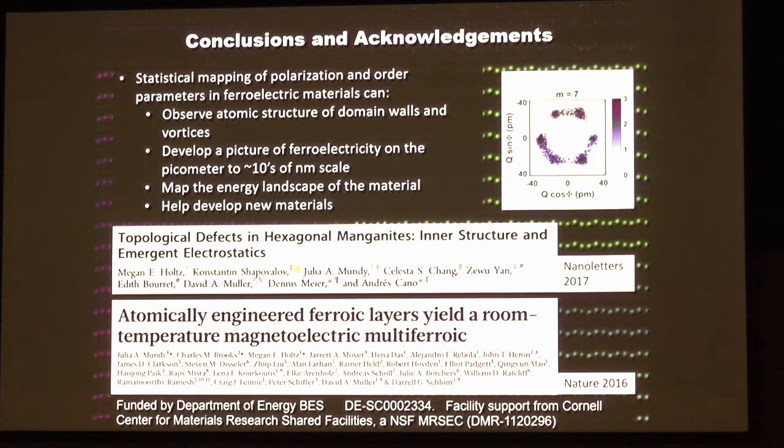Yeah. Thank you for the talk. Very beautiful images. I was wondering if this double layer of iron that you have in different superlattices, can you comment about if there is some kind of charge ordering there and if it evolves with m? We did look for charge ordering with EELS, but we were never able to see it in those structures experimentally, at least. So we're assuming that the ferroelectricity in these superlattices is all coming from the 113 ferroelectricity. Okay.